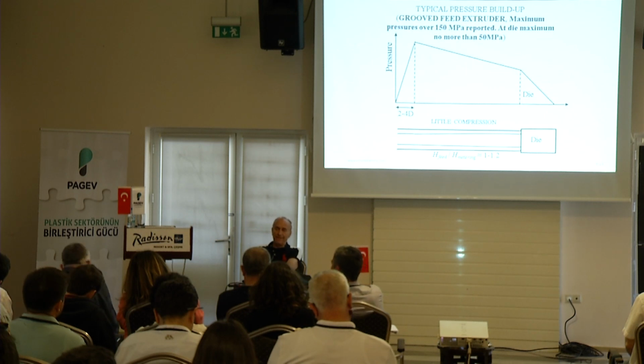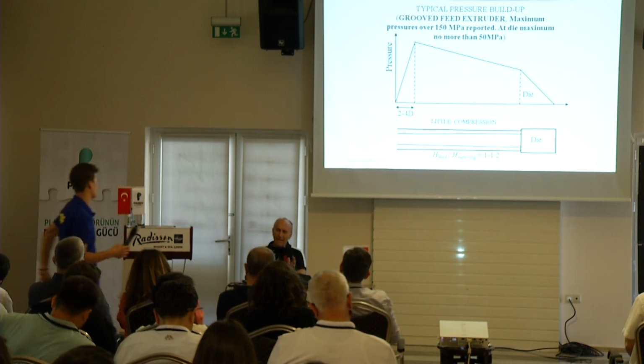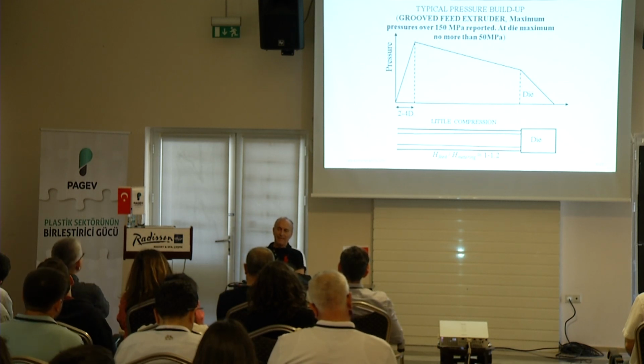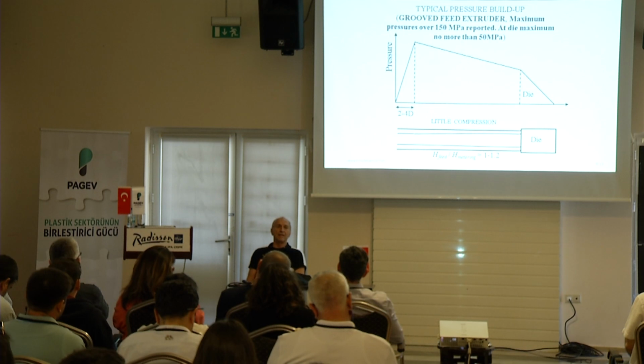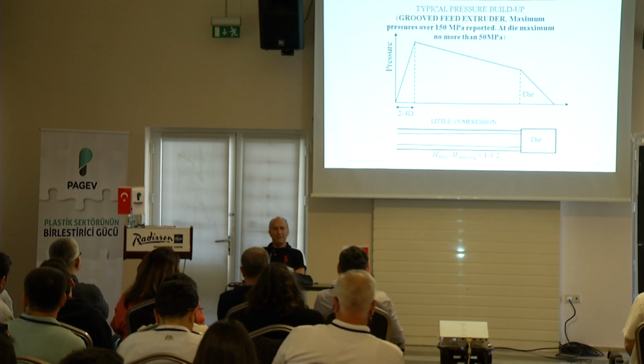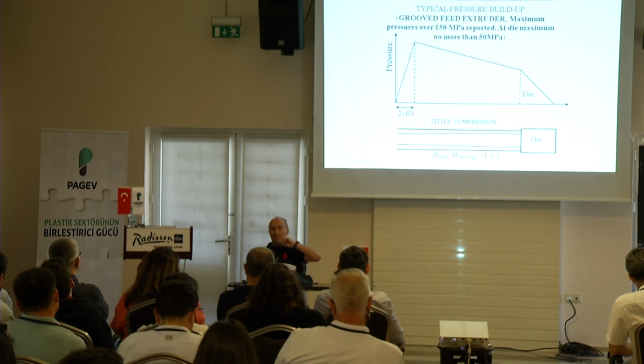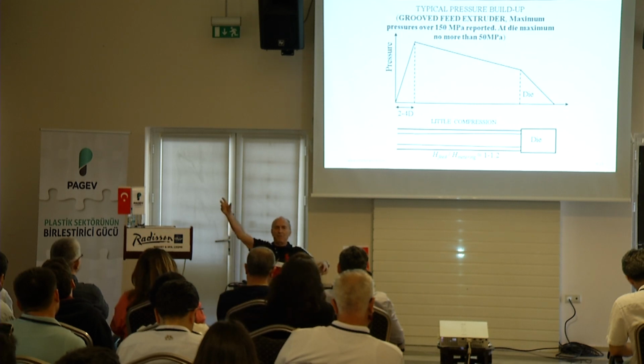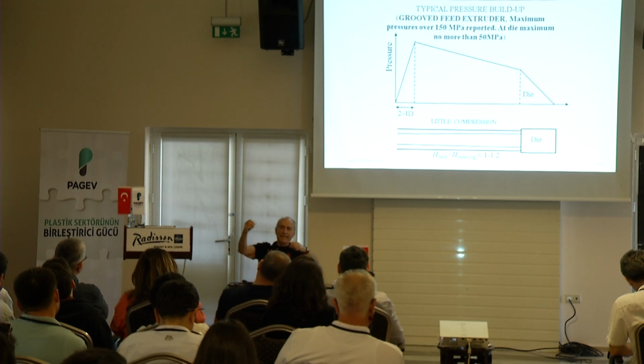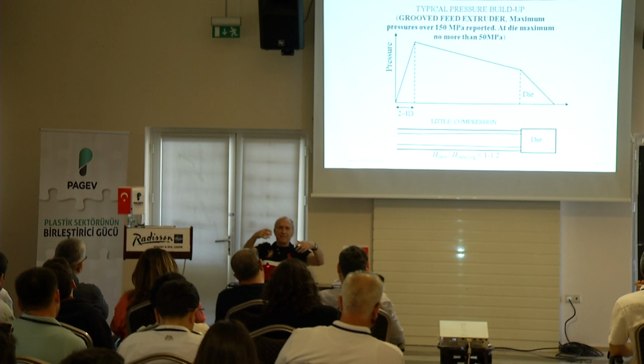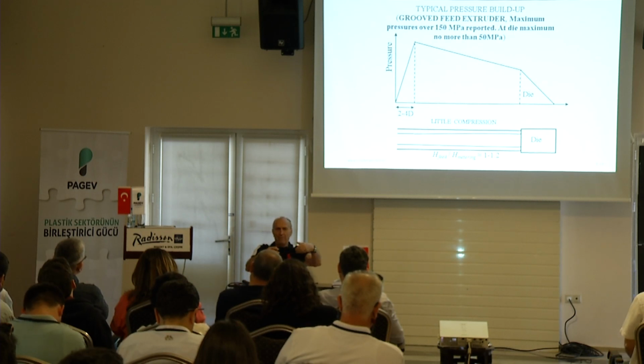And if you have good pellets, but with other stuff, sure, it may work. But my experience is that I would recommend grooved feed extruders for good material, good pellets. I would not recommend it for recycle, except if recycled polymers are converted to good pellets. I would not recommend it when you mix virgin polymer and recycle together. The virgin polymer would have nice pellets, 3 millimeters in diameter. The recycled would be probably cut up, like you extrude and then chop it up, and you have irregular shape. Irregular shape generally is troublesome, but who knows?